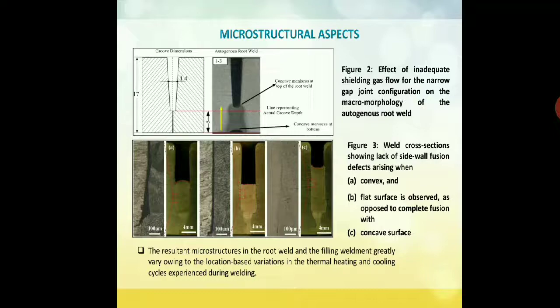Use of high laser power or low shielding gas during root welding can result in a concave meniscus at the bottom. It is because of the upward capillary action of the weld metal, as you can see in the figure. And interestingly, the shape of the surface of the weld after each pass can determine the lack of fusion. One report says that lack of fusion takes place in the convex and flat surfaces of the weld joints, while the concave surface of the weld joints represented the complete fusion.